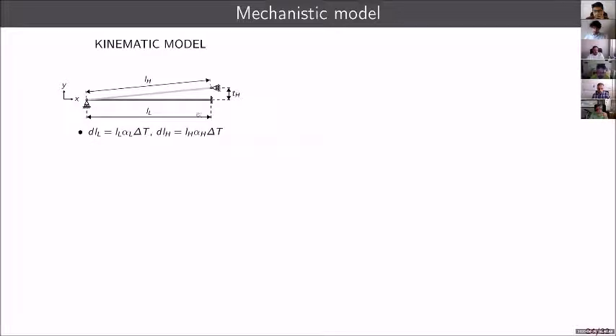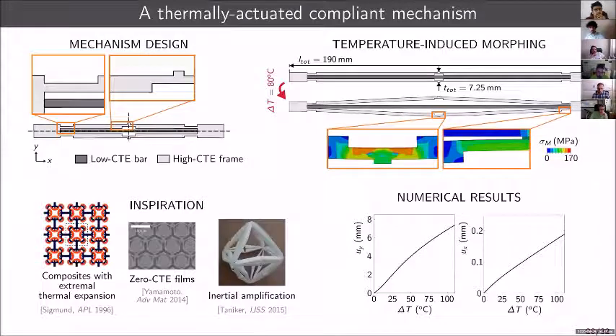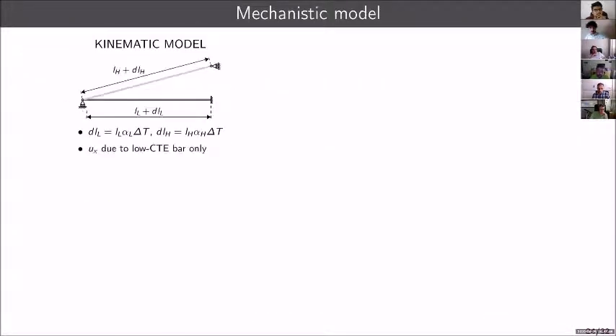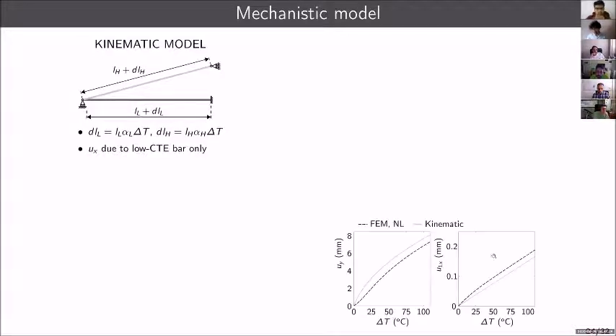However, the big assumption here, and you can see it from this animation, is that the horizontal displacement is only due to the low CTE bar. So they assume that the low CTE bar expands, and the high CTE bar will also expand, but only rotate and create this vertical displacement, as you can see over here. However, comparing it to our numerics, you can see that the results are not that great.